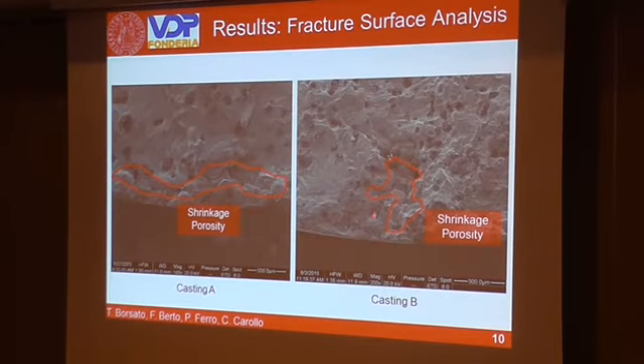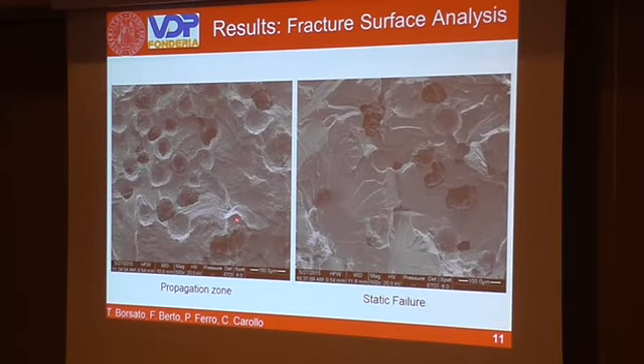This could be attributed to a better inoculation treatment that induces the higher nodule count. So we have a greater graphite expansion that reduces the shrinkage porosities. The cracks propagate in the propagation zone around graphite nodules, while final failure happens in a brittle manner by cleavage for all the specimens that were observed.